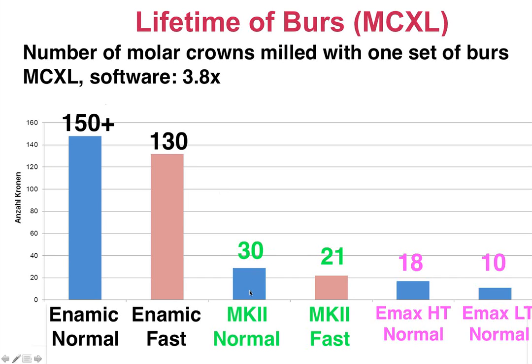Even though it says 30 blocks for Mark II, I think we're usually at around 20 blocks for a single set of burrs with our Mark II materials. And Emax down here at 18 and 10 for number of blocks you can get for a single set of burrs. So this is maybe the most stunning result as far as milling behavior with respect to how many blocks you can mill on a single set of burrs.